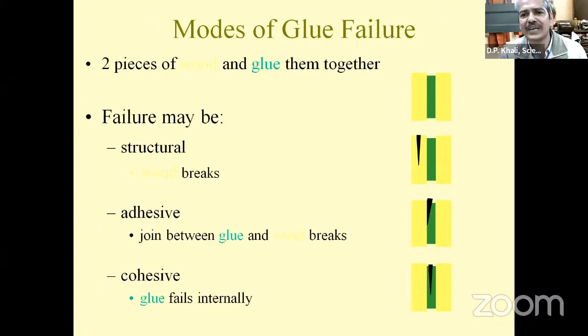The topmost, you can see the green one is the adhesive layer, the yellow one is the wood. If wood failure is taking place, so this is a structural failure. So this is due to process parameters. Somewhere we have done wrong with our process parameters, whether we have applied less pressure or temperature is not sufficient, something related with process parameters.